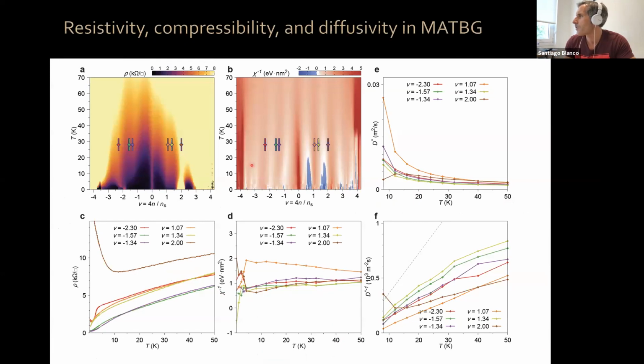Juan Hernandez Tecorralco is asking whether the flat bands in magic angle bilayer graphene could be related or be evidence of ferromagnetism in this system. Well, I would phrase it in a different way. When you have a flat band, there's competition between kinetic and interaction energy. In the limit where your bands are very, very flat, interactions dominate completely, and hence flat bands are typically fertile ground to have various types of ferromagnetism, because now your interaction energy dominates over your kinetic energy. So it can be favorable for the system to polarize, and it can be ferromagnetic in the sense of spin ferromagnetism, but it can also be ferromagnetic along a different flavor. So flavor polarization is something that happens in flat band systems, and it happens also in magic angle bilayer graphene.